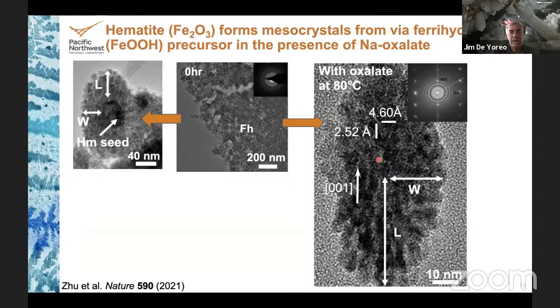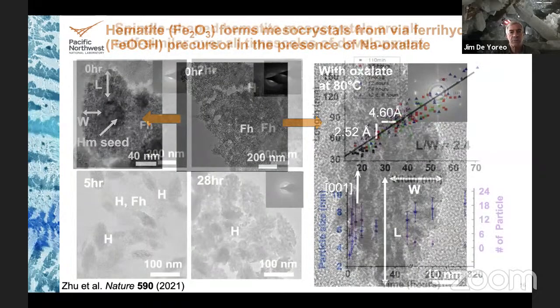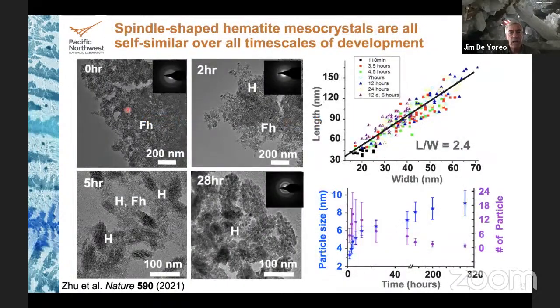So this is not a random process, it's deterministic. If we look at time points, these are ex situ images. We've done the same thing with cryo, and I will show you in situ TEM shortly. You can follow this process from ferrihydrite to ferrihydrite with some isolated particles of hematite, to hematite spindles surrounded by ferrihydrite, to all hematite spindles.